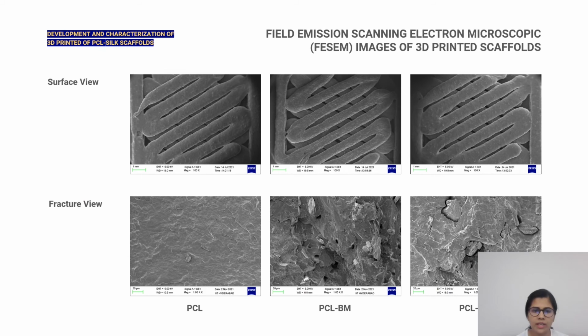Next, we have characterized these scaffolds. Field emission scanning electron microscopic images of these 3D printed scaffolds were taken to observe the morphology. As you can see, Bombyx mori with PCL has shown more roughness when compared to Antheraea mylitta with PCL. The reason for this is that the density of Bombyx mori is less, so to form those particular percentages, we need to add more Bombyx mori when compared to Antheraea mylitta. And with the addition of silk, there is an increase in the overall roughness of these scaffolds.